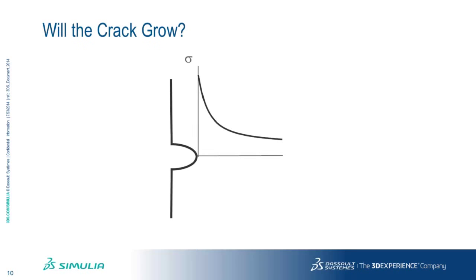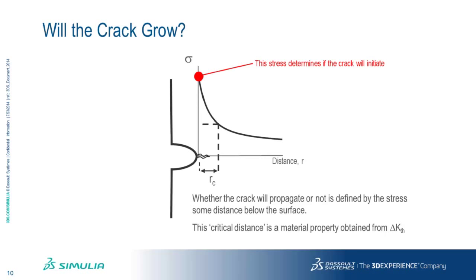We can then check whether the crack will actually propagate or not. And we use the information on the subsurface stresses in the model. So what we've shown here is the stress reducing as we move into the material. And whether the crack will propagate or not depends on the stress some distance below the surface. And that distance is a material property, and it's called the critical distance for the material. In the FE-SAFE database now, we are starting to put critical distance values for some of the materials. If you don't know them, it's quite easy to measure. There is a simple approximation formula as well. So this stress determines the life to crack initiation. This stress determines whether the crack will propagate or not.